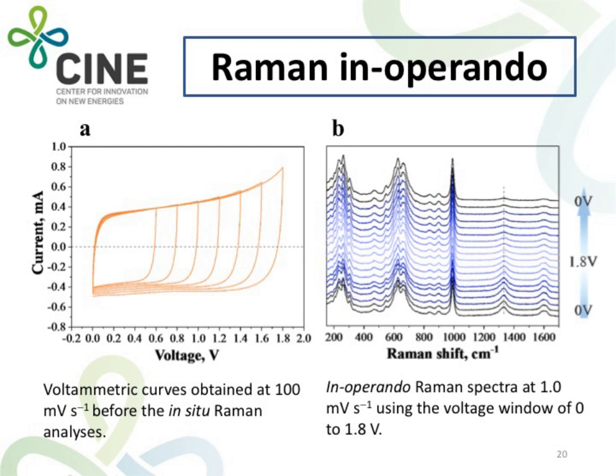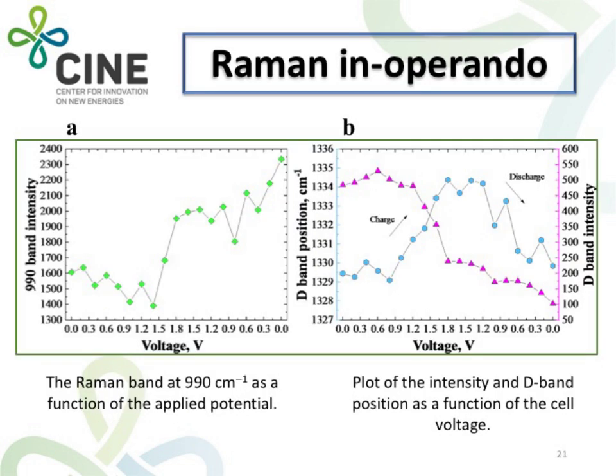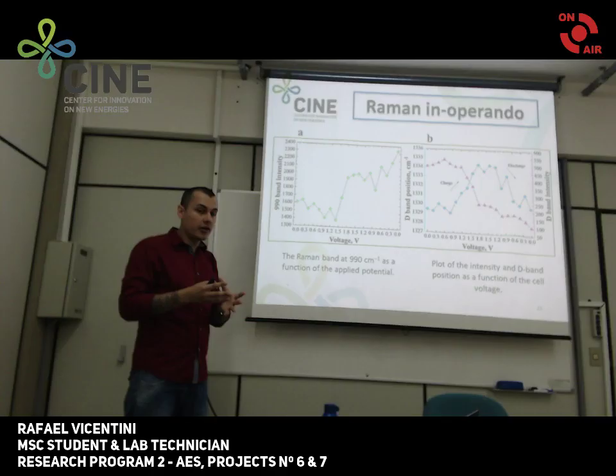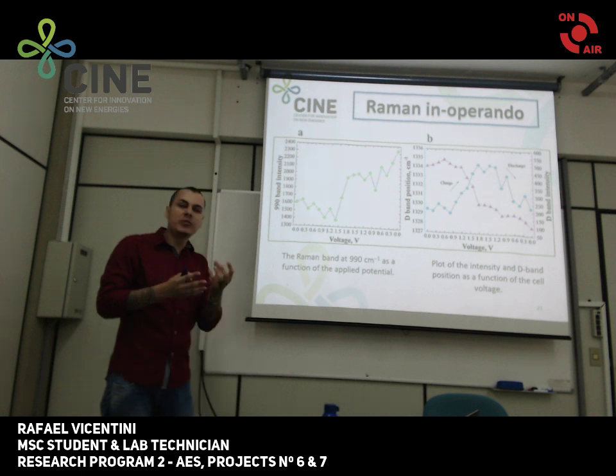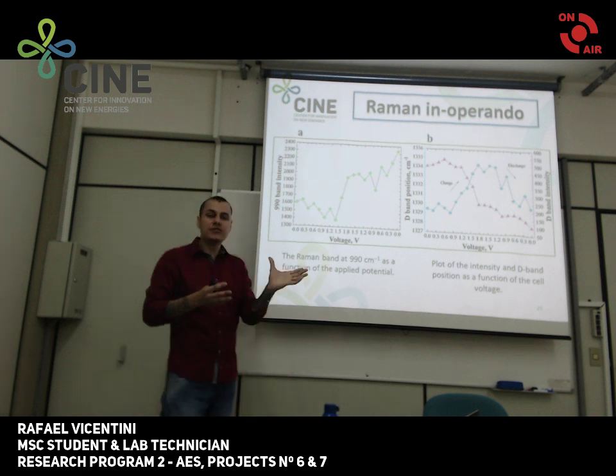In this graph, the D-band position starts at 1329, then goes to around 1335, and then goes back to the initial position. Here, we can observe a reversible shift in the D-band position, and in this paper, we found a relationship between the D-band shift and the charge storage mechanism.